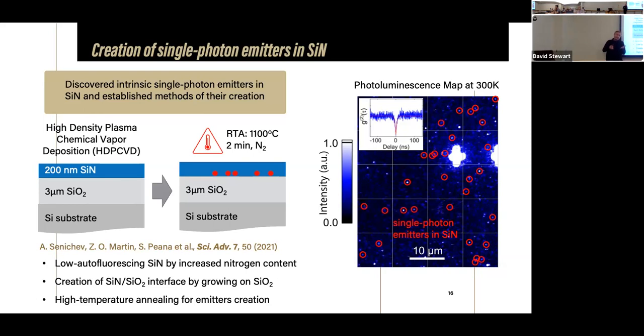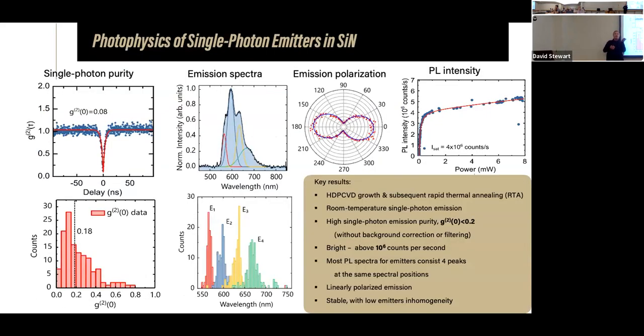But the idea we have is that when you do this rapid thermal annealing, because the thermal expansion coefficients for silica and silicon nitride are different, you create strain, and strain eventually causes these defects. So these defects are most probably strain induced, and we're working with material scientists now at Harvard, trying to prove it, and also at the Technical University of Denmark. We find this good news because you could control strain in many different ways, including electrical.